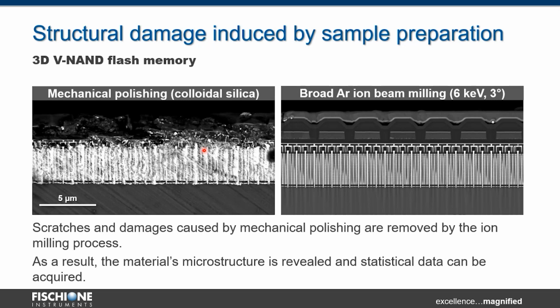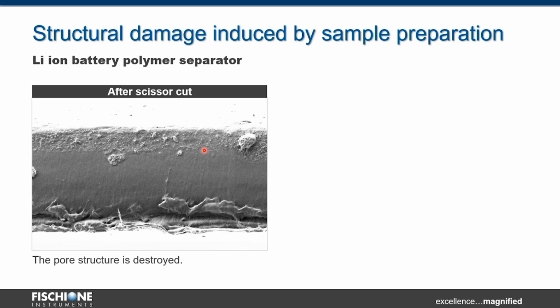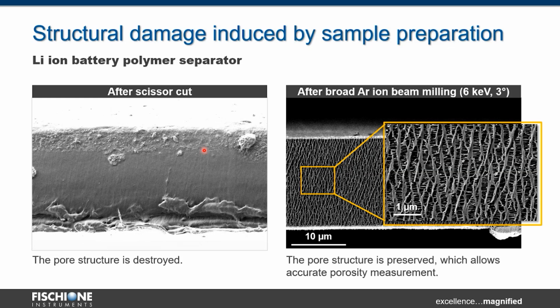for failure analysis. Here we have a lithium-ion battery polymer separator that was cut by scissors. This is a very thin and fragile sample. There is no other technique that can be used to prepare that sample and preserve all that porosity structure. But if you use argon ion milling, you can nicely see that the pores, those structures, are preserved. You can zoom in and do accurate porosity measurements if you need them for your research.